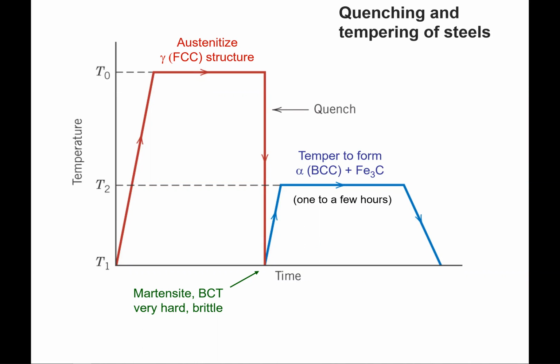This looks a lot like precipitation strengthening. And so what we have here is we're going to start off at some T1, say room temperature. We're going to go ahead and heat up our steel so that we austenitize it. That's our first step in all these processes. So we form a complete austenite structure. We undergo a quench back down to room temperature, and we know from the TTT that this is going to form martensite. Now, I said martensite is very strong, it's very hard, but the problem is that it's too brittle to use in that particular form.